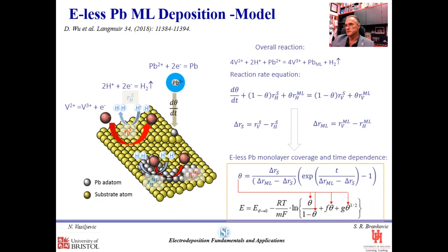How this really happens is an interesting catalytic phenomenon, and the description of it is a little bit longer. I'm going to just give you a few aspects of this process. Basically, we have vanadium as an electron donor, and then we have H+ and Pb2+ ions that are reduced. So what we really have is a balance between electron donor reactions, which represent the vanadium oxidation reaction on the clean gold and on the gold surface covered by the lead monolayer, and then the electron consumer reactions, which are the hydrogen evolution reaction on the monolayer lead-covered gold, hydrogen reduction on the clean gold surface, and the reaction of lead deposition.